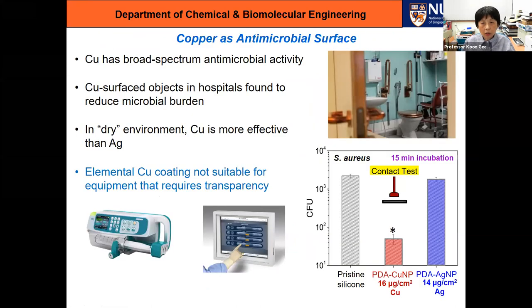So we zoom in on using copper because we know that copper has broad spectrum antimicrobial activity. And a number of studies have shown that in hospitals, when certain fixtures are changed to copper-coated fixtures, like door handles or toilet seats and bars and so on, the microbial burden has been reduced. And we ourselves also did some tests, and we showed that copper is much more effective than silver in a dry environment like our normal rooms, hospital rooms or our house rooms.